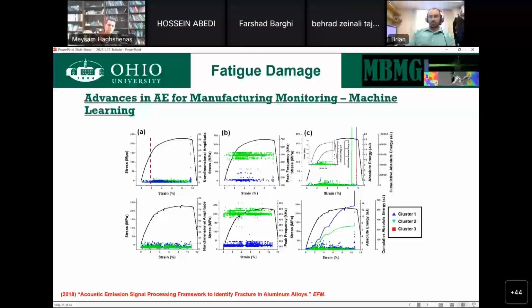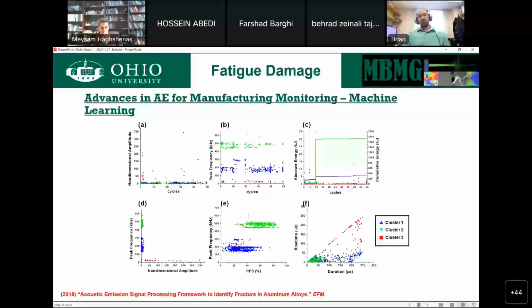So the DAQ that we use to collect this data has an operating frequency that can bias the signal to about 150 kilohertz, and that's about what you're seeing here. We can then extend this and plot it in different forms and see how different frequency contents exist. We can do it in fatigue tests, where you can do this across any loading scheme you want to do and try to understand how the material is evolving.